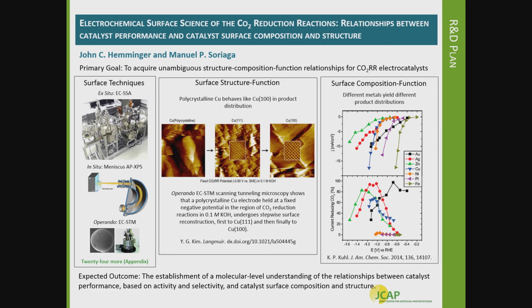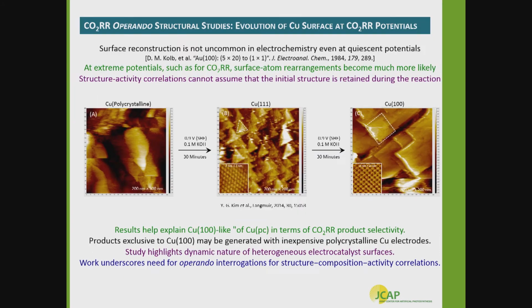And so as an example of the structural transformation, in situ electrochemical STM, which is work being done by John Heminger and Manny Soriaga, has been able to detect, for example, on copper, which is one of the most widely studied heterogeneous catalysts for CO2 reduction, a remarkable transformation where polycrystalline copper surfaces under electrochemically active conditions for CO2 reduction undergo nanoscale transitions to faceted 111 and then 100 surfaces.